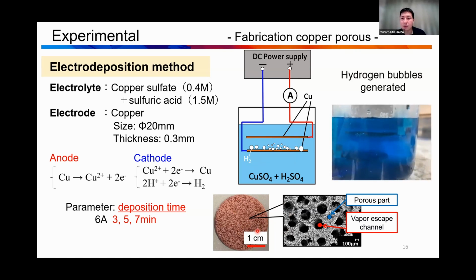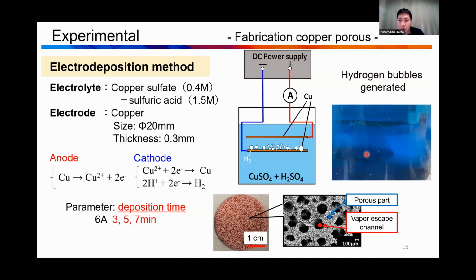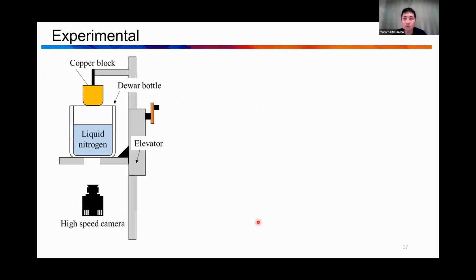So this one is an actual video of making the copper porous plate. Hydrogen bubbles are coming out from the cathode, and finally we get this porous plate. We apply this porous plate to the sample. So this is the experimental process. It's very simple. This is a dewar bottle, and liquid nitrogen is poured in here. We use a copper block as the test specimen, and the dewar bottle is flat on the bottom surface to visualize the quenching phenomena.